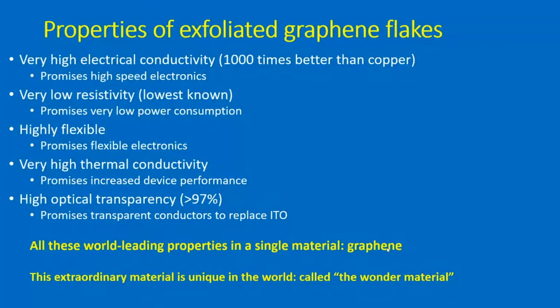Now, the 2 Manchester scientists didn't really get the Nobel Prize just for Scotch tape, because if the graphene had been no good, people would have said, well, a silly thing to do, a silly experiment. But they got the Nobel Prize because they got the graphene, and then they did experiments on it, and a single layer of graphene is transparent, so you can't see it. So think of doing experiments when you can't see it. Think of putting contacts on when you can't see it. So they did these really difficult experiments, and what they showed was amazing, and that was this layer of graphene had conductivity 1,000 times better than copper.